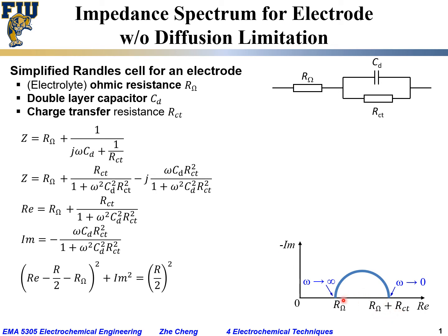So based on this, if we can measure the impedance spectrum, and assuming the contribution from the counter electrode is negligible, then the overall impedance is coming all from the working electrode. From here we can get the ohmic resistance associated primarily with the electrolyte, and we can also get the charge transfer resistance if the diffusion limitation is negligible. If there's no diffusion limitation, the species can come and go as fast as needed, okay? For this circuit, if we measure one impedance spectrum, we would know the ohmic resistance, and we would know the charge transfer resistance if the diffusion is very fast, the mass transfer is very fast.